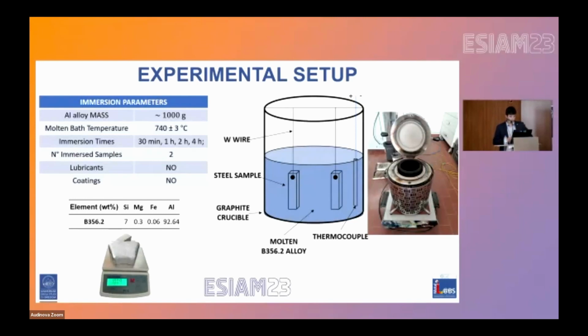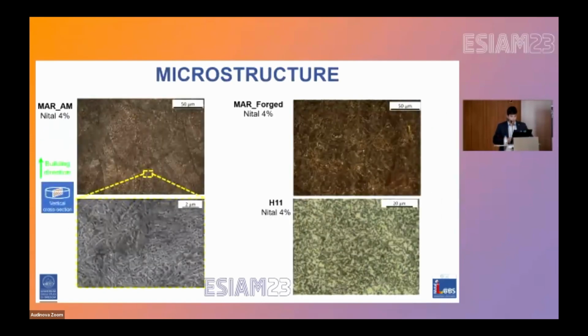Then the cross-sections of the immersed samples were cut and mounted in hot resin to conduct a metallographic analysis. Before the immersion test, microstructural characterization was also conducted. Here you can see the typical microstructure of a vertical cross-section of the AM samples with a semi-elliptical melt pool boundary clearly visible also after the aging treatment. No porosity was detected within the microstructure, suggesting the achievement of a fully dense part. At higher magnification, the scanning electron microscope image instead revealed an extremely fine continuous cellular structure, typical of AM parts.